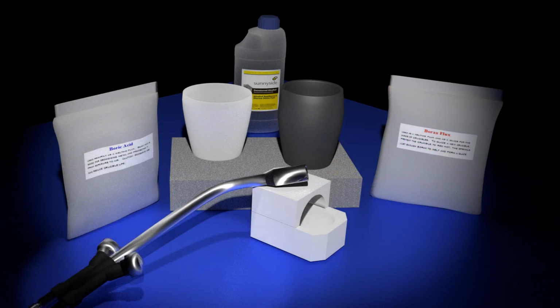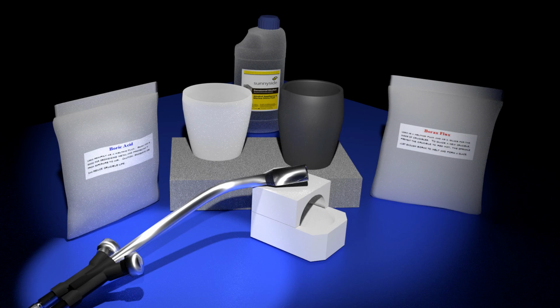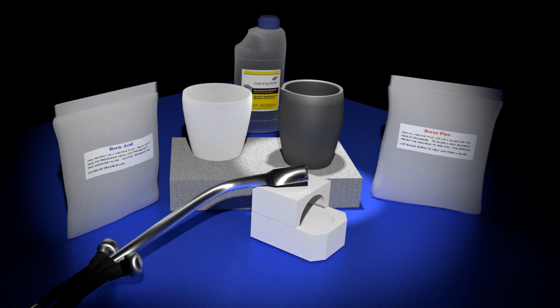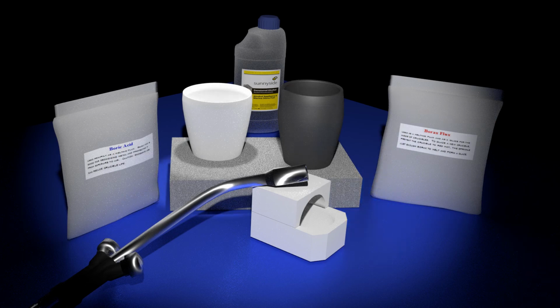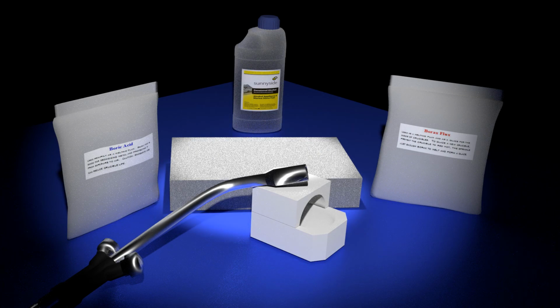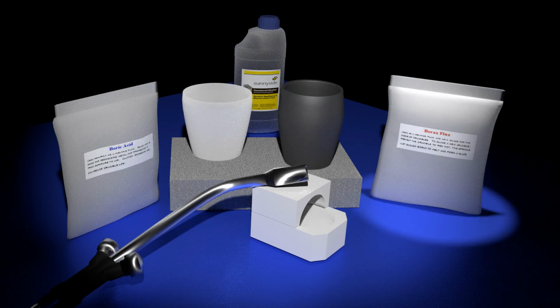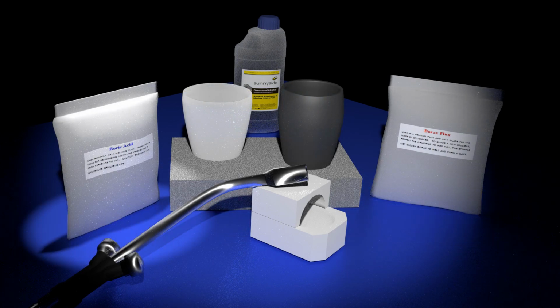Melting torch. Use a torch made for this purpose. The common propane torch simply will not provide enough BTUs to do the job. Crucible. You can use a standard clay graphite crucible, a ceramic cup-shaped crucible, or you can use a burner ceramic crucible. Crucible rest. Any refractory material, like a brick or a cinder block for example, will do the job. Flux. Common fluxes that are typically used include borax, boric acid, or a combination of the two. Alcohol.